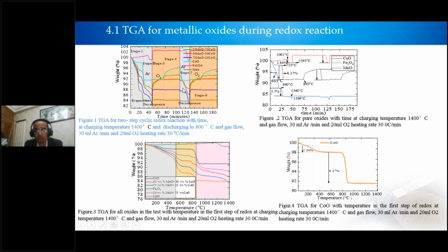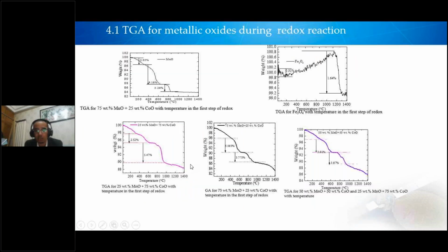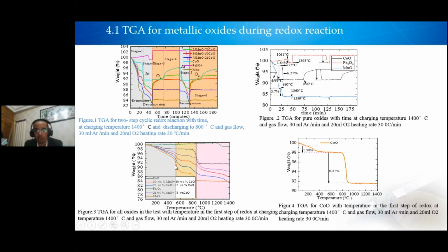So this is how we see which proportion of metallic oxide is important for cyclic stability, for further study. Well, this is the weight reduction with time for the pure oxides: cobalt oxide, iron oxide, and manganese oxide. So we checked the pure oxides. In this case, for the first cyclic redox reaction, we analyzed all six compositions, and then the first charging process.